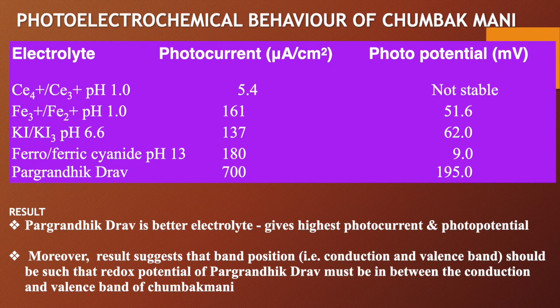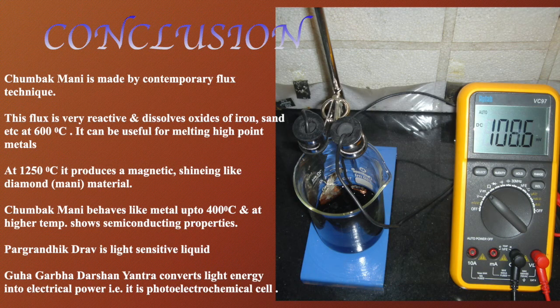And moreover, it suggests that the band position should be such that the redox potential of our electrolyte Pargrandhik Drav must be between the conduction and valence band of the Chumbak Mani. See, there are many things which still need to be done. So in short, this is how we are measuring it. And in short, I can say this is the whole setup after making it.